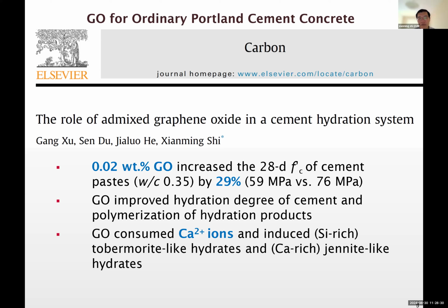That's a different story. But graphene oxide itself is not thermally or electrically conductive. But the negatively charged nanoplatelets consume the calcium cations in the juice. Again, going back to the concrete being a solid sponge, when it's partially or fully water saturated, you basically got this highly alkaline juice, the so-called concrete pore solution, and you have calcium ions. And because of this interaction between the negatively charged nanoplatelets and the calcium cations, and some other ions, then you induce different kinds of hydration products, such as